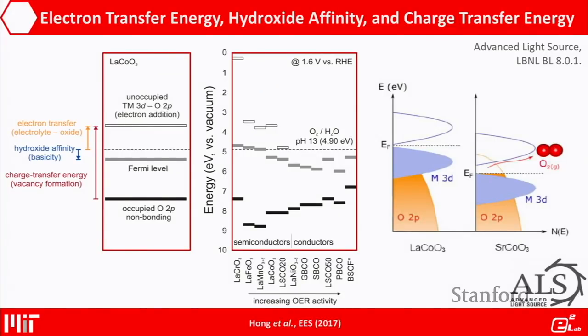From early perovskites to late perovskites, you can increase the covalency of these metal-oxygen bonds. Correspondingly, you can see in the gray bars that the Fermi level comes down. In the open bars, the unoccupied states for the late transition metals on the right become metallic, and the oxygen p band stays relatively constant.